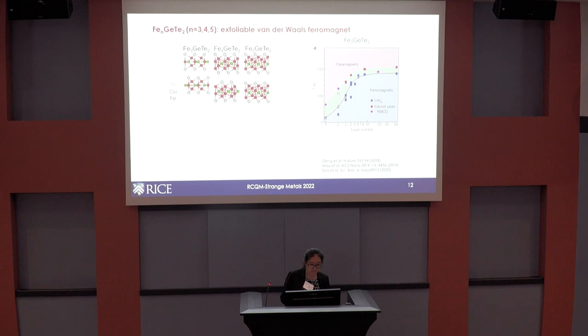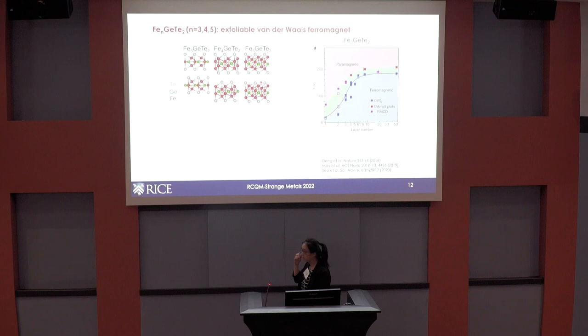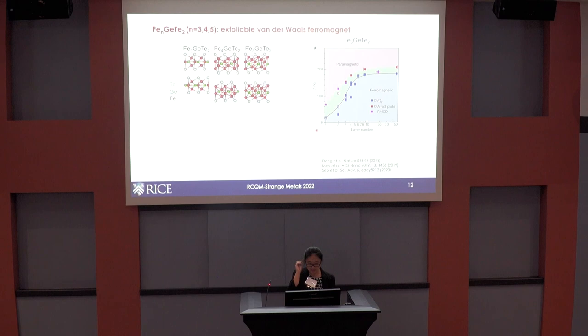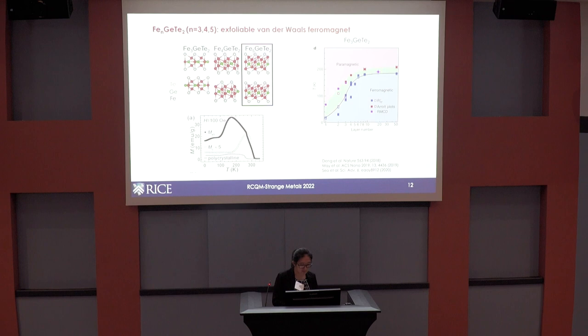These three members of the FGT family are all made of stacking Van der Waals layers. The gray sites are tellurium, the green sites are germanium, and the difference between Fe₃₁₂, Fe₄₁₂, and Fe₅₁₂ is the amount of iron within each layer. These materials retain long-range ferromagnetic order down to the monolayer regime when exfoliated. I'll focus on the last member, FGT 5-1-2, which has the highest Tc in the family — somewhere between 250 and 320 Kelvin, depending on crystal preparation and exact stoichiometry.